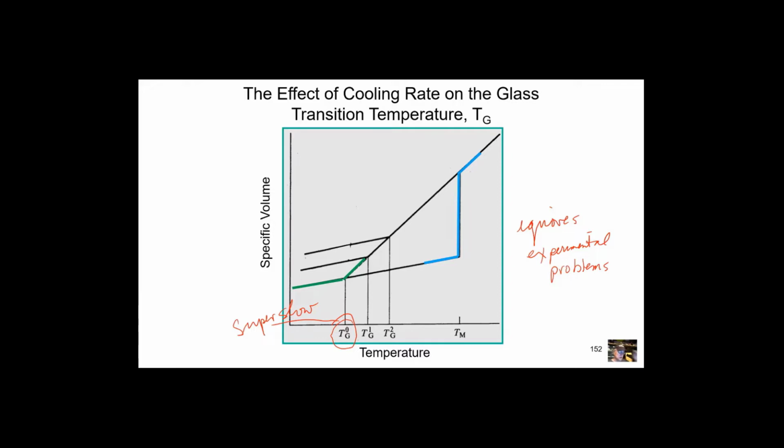I should mention one other thing about glass transitions. We're talking about this sort of volume way, and that is an actual way that they can be measured. But in modern labs, they're often measured by things like solid-state NMR. And they can specifically go in and look at that benzene ring on the polystyrene chain flipping around. They can specifically go look at a methyl group rotating around, or the other kinds of motions you have. And so you get slightly different numbers out of glass transitions according to what technique you use as well. So it's kind of a messy situation.